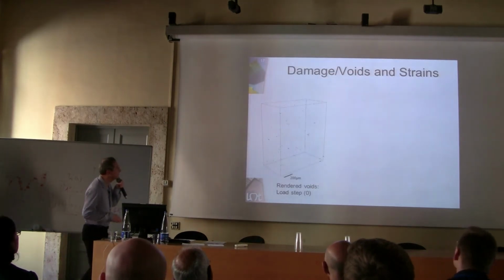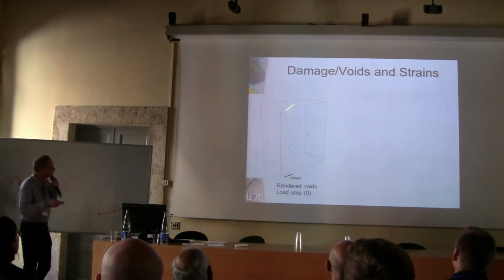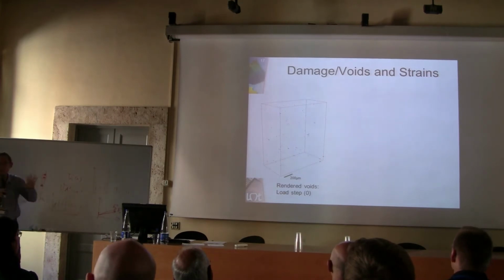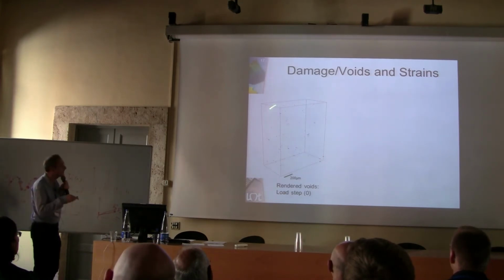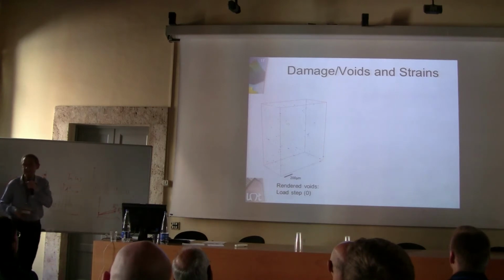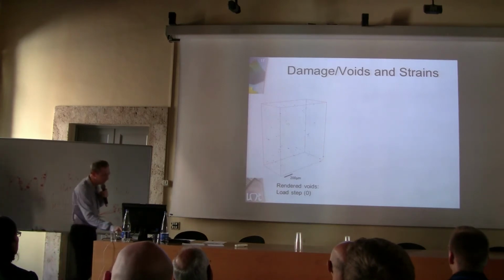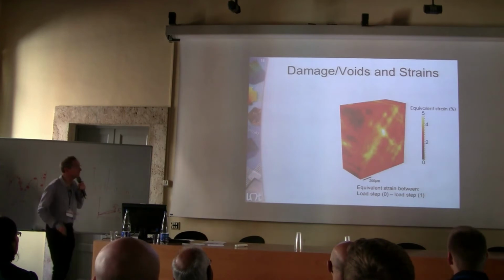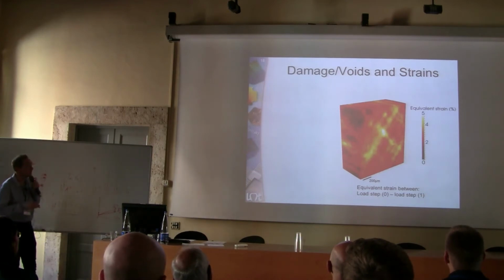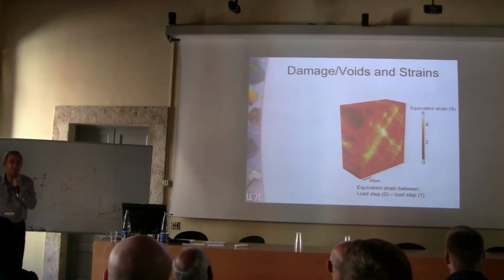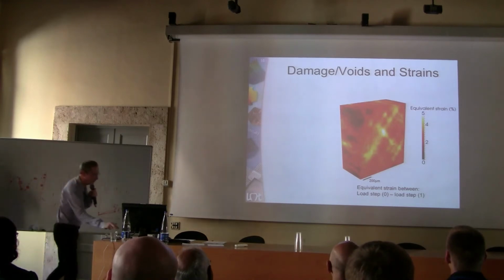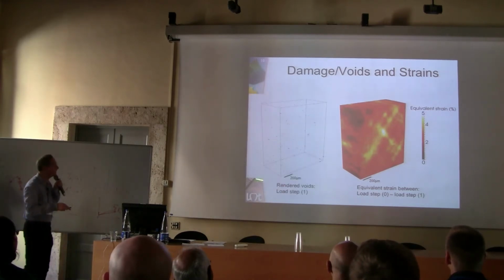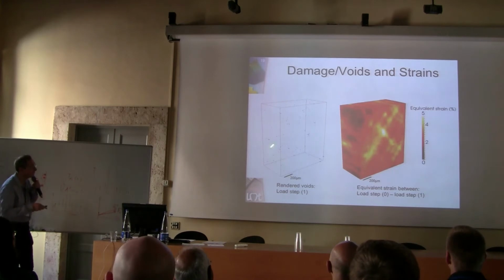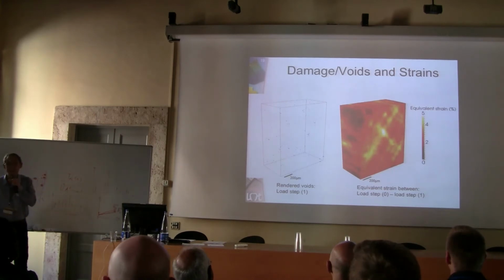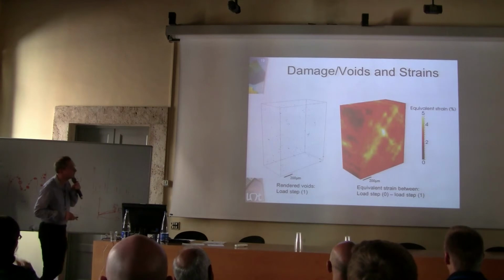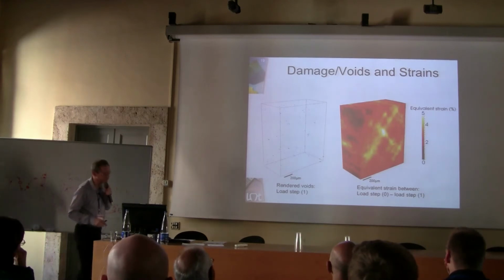This is now the volume in the reference configuration, thresholded just to reveal basically all the secondary particles in the material. Then, for the first loading step, here you see a 3D rendering of the equivalent strain field, and in parallel, the thresholded volume again. Basically, there is nothing happening there in comparison with the reference configuration.